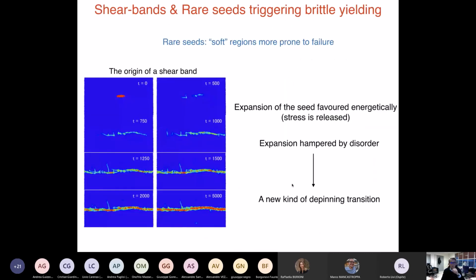Now, what we are doing right now is showing that the existence of this shear band in the case of brittle behavior is very, very similar to the rare seed that we discussed in the case of the random field Ising model. So what you have here on the left is a kind of movie of the life of a shear band, or the origin of a shear band. Before, in the movie that I showed you, it was too fast. Now what you're seeing is that a shear band starts from a seed, and then as time increases the shear band starts to propagate from the seed, becomes larger and larger, and then invades the whole system. Once it has invaded the whole system, it's easier for the system to deform because it contains a shear band in the middle, in which the deformation is easier.